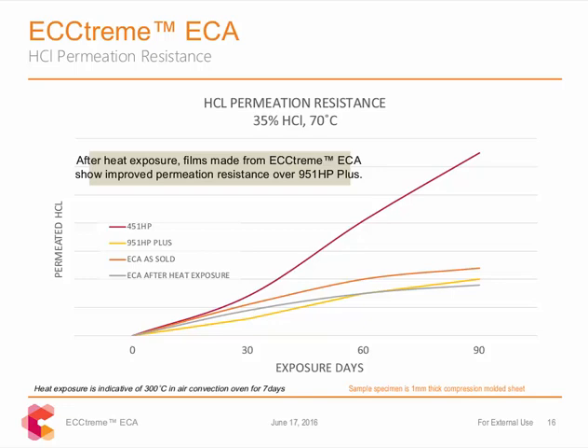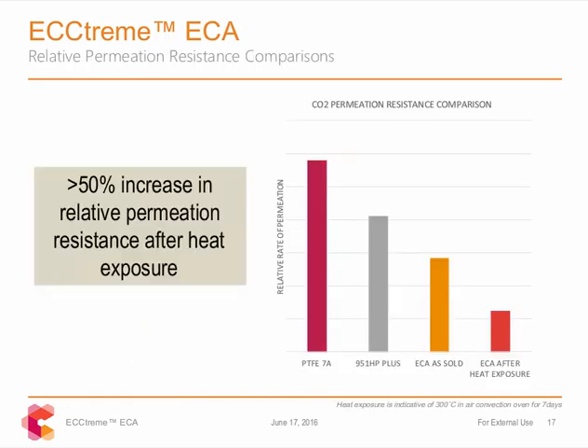HCl is a well-known permeant of fluoropolymers, and compared here to our Teflon PFA product line that is well known for having industry-leading permeation resistance, ECA actually performs as well or better than these leading materials. We were even honestly surprised by the performance of ECA when compared to specifically our 951 HP Plus product line, which is known specifically for its resistance to permeation from HCl. Another example of ECA's resistance to gas permeation is shown here, shown to outperform both PTFE and, again, 951 HP Plus, both before and after exposure to heat. So you can see here the increase in relative permeation resistance compared to other industry-leading materials.